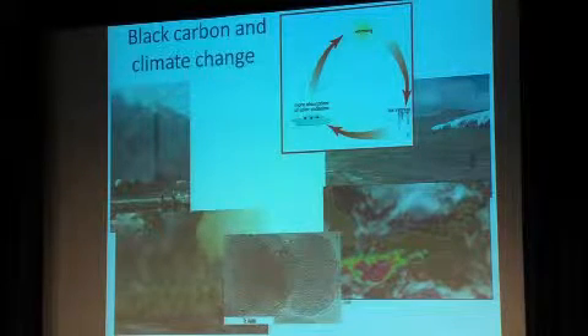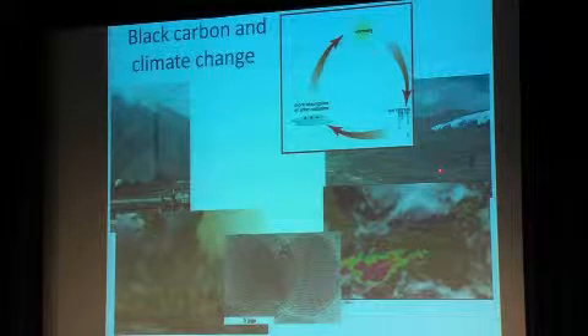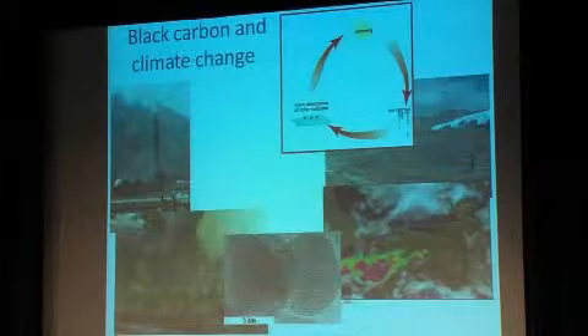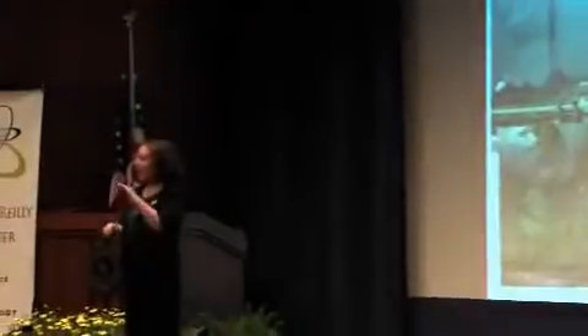Because they're small, if they get up into the upper atmosphere, they can move a lot, and they are changing the albedo of ice in Antarctica. I've worked with Diane McKnight on some research looking at nanoparticles and microbes in Antarctica. This is one of her pictures. When these nanoparticles of black carbon, and carbon black probably too, deposit on the glaciers, they actually make the glaciers darker colored. And so the amount of light that's reflected off the glaciers decreases, and you get more melting of the glaciers, which increases the feedback loop: the less glacier you have, the less albedo, the more solar energy is absorbed instead of reflected.